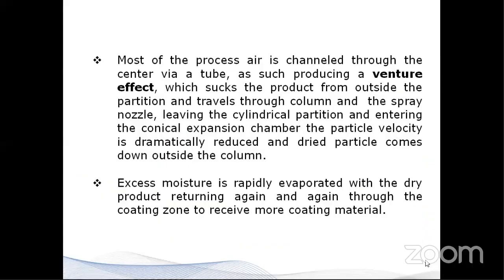Most of the air is channeled through the center Wurster tube, producing a venturi effect which sucks the product from outside the partition and draws it up the column. The spray nozzle is positioned leaving the cylindrical partition and entering the conical expansion chamber. The particle velocity is dramatically reduced and the dried particles come down outside the column. Excess moisture is rapidly removed with the dry product cycling again and again through the coating zone to receive more coating material.